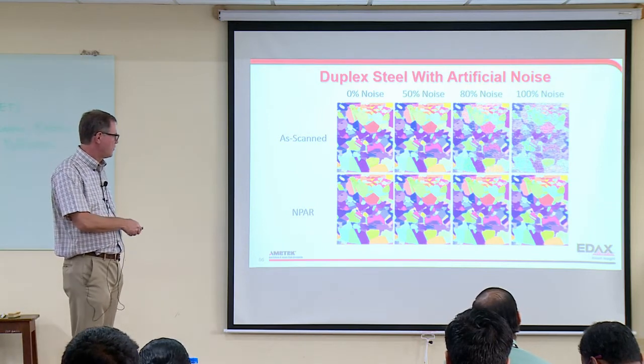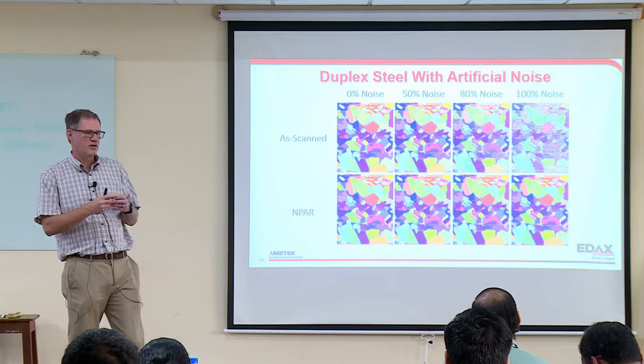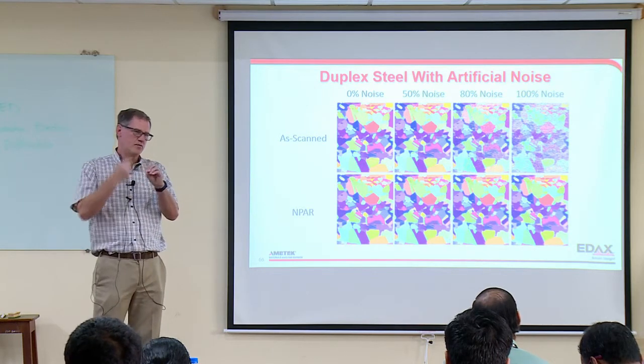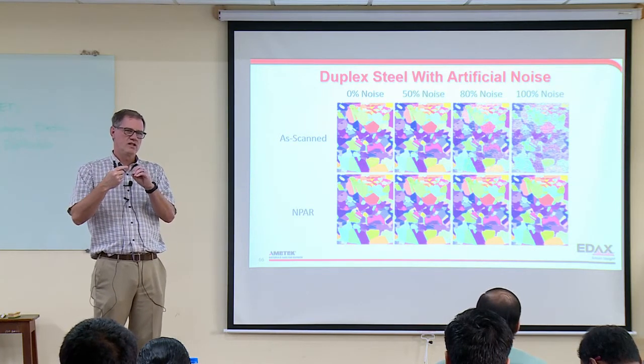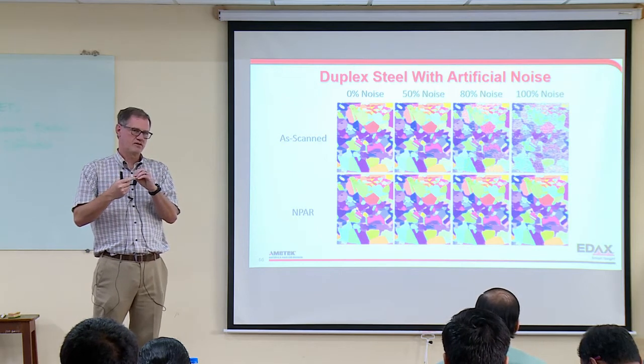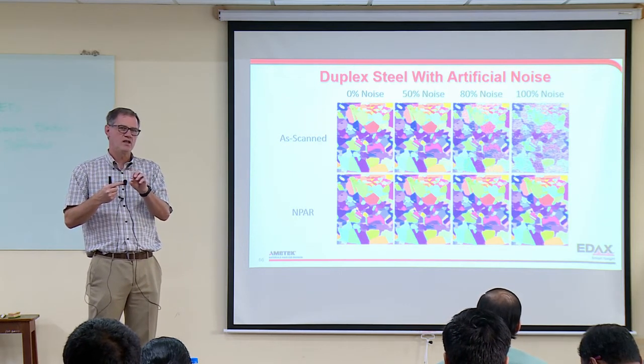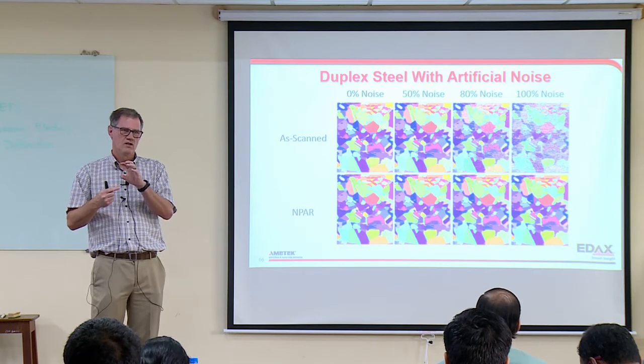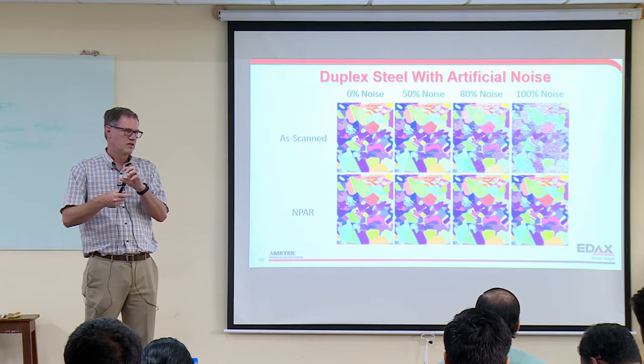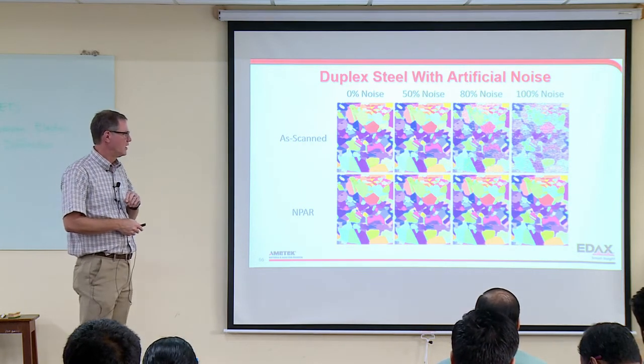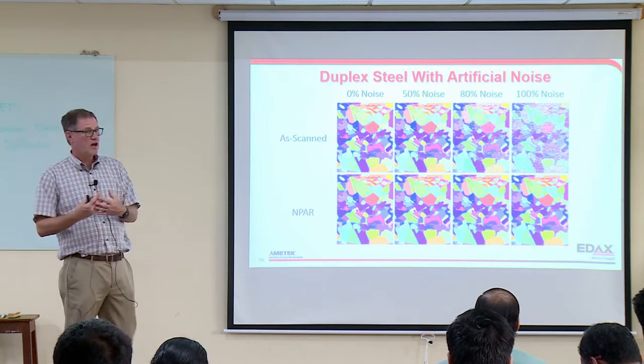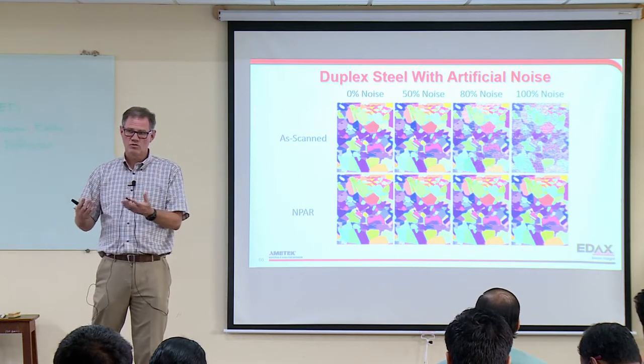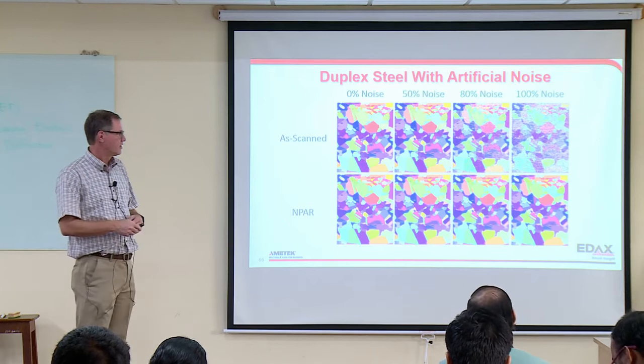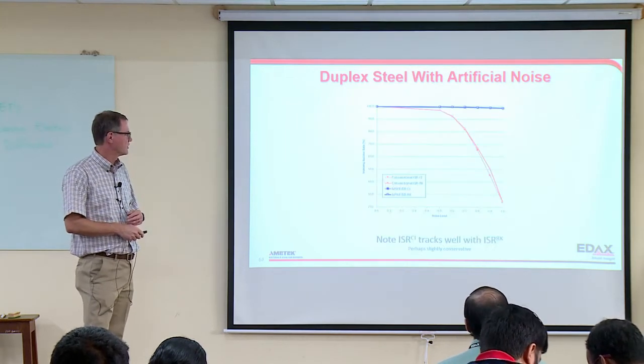It's almost as if, because if you're using a hexagonal grid, you have this point and you have the 6 neighbors, it's like you're increasing the exposure time by a factor of 6. So you retain the speed that you had for one pixel, but by averaging in the others, it brings in the others well. And part of that is our ability to deconvolute patterns at grain boundaries works well, so we're able to do this. There are situations where it won't work, and I'll show you examples.